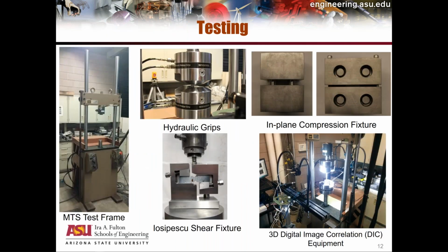So at Arizona State University, we have reasonably good, if not excellent, testing facilities. On the screen, you see a variety of test fixtures and testing frames that we use for testing. So on the left, we have an MTS test frame with a capacity of about 22,000 pounds. We have an Instron machine where the capacity is roughly 110,000 pounds. So we can test materials and take it to those levels of loading if necessary.